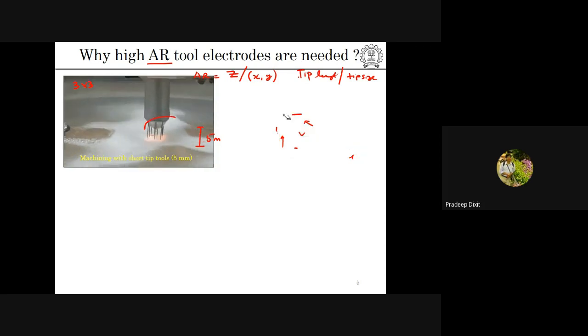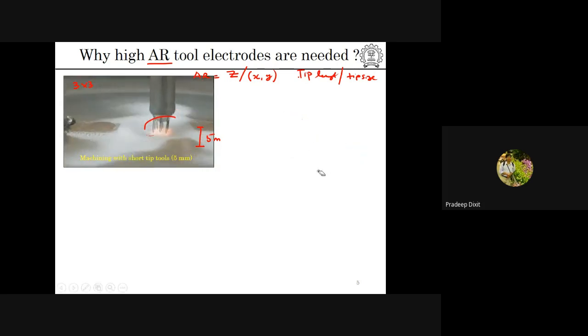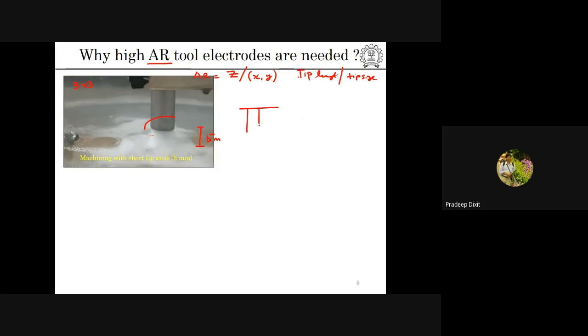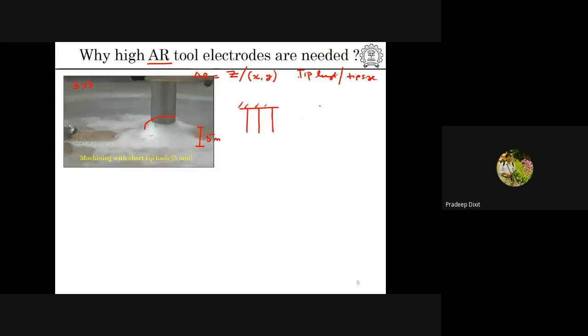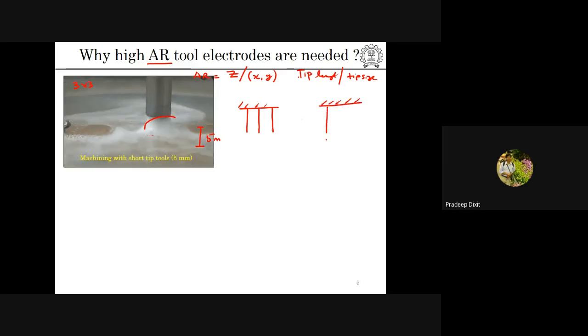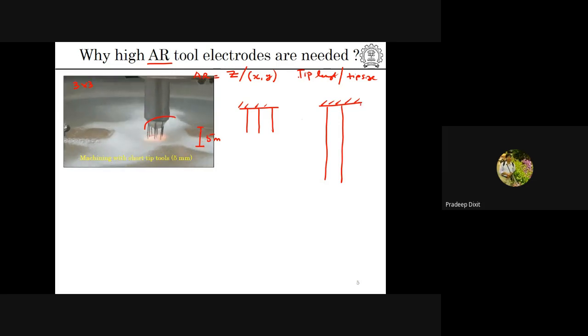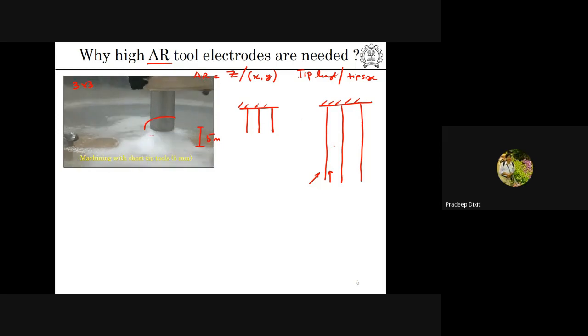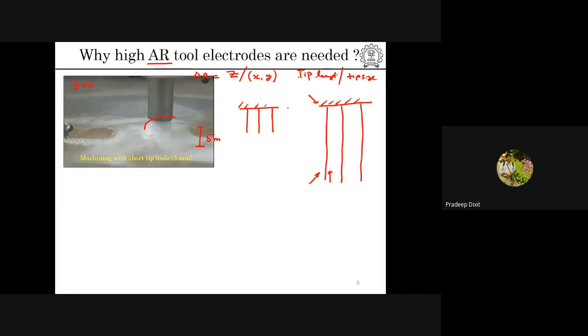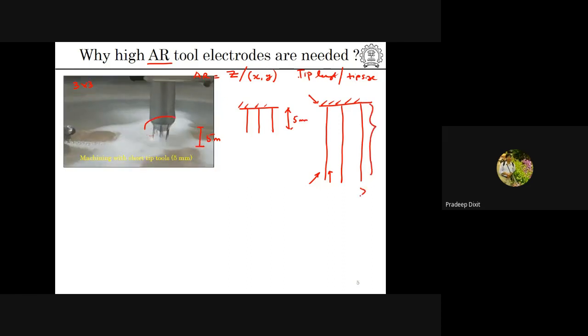Now, in order to resolve this particular issue, what we thought is that instead of this kind of situation here, if we create a very long tip, for example 3 times longer like that, this problem would be reduced. Why? Because first of all, this cold place is very far away, and the water vapor will take more time to reach the cold place, which is basically the base plate here, right? So if we increase the tip length from, let's say, 5 millimeter originally to, let's say, 10 to 12 millimeter, then the problem would be reduced, and that is what we have done.